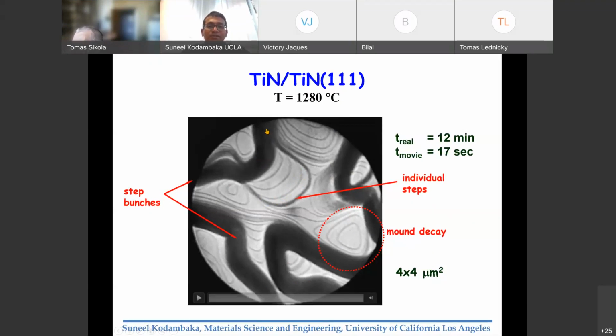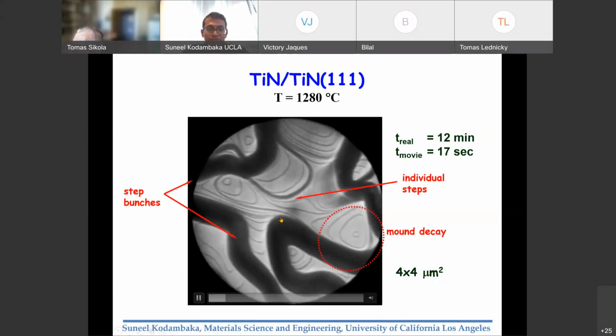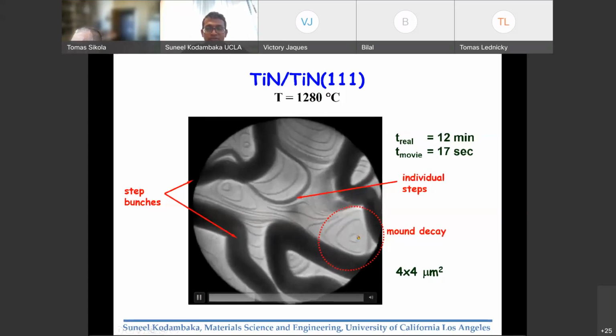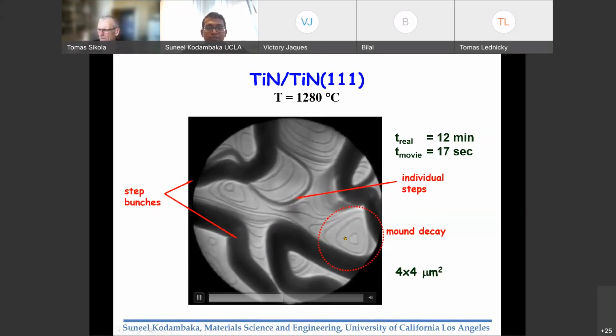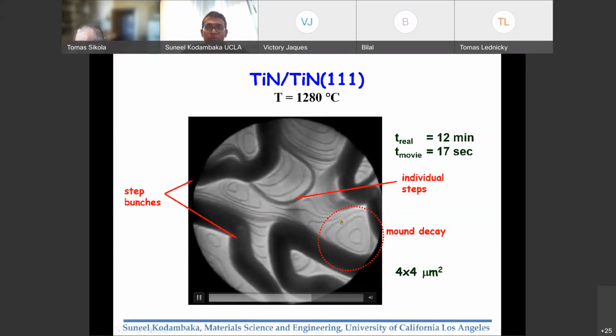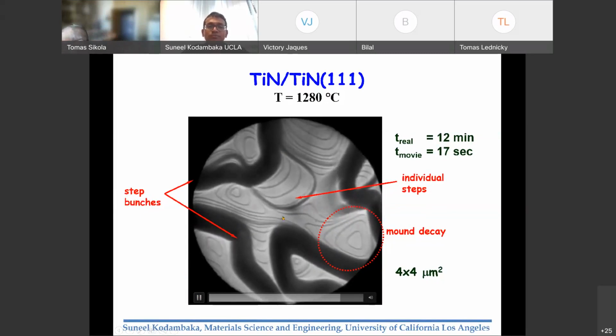These darker lines are thick step bunches and grains within this film that was deposited on the sapphire crystal. And what you're looking at here is the decay of these, what I call mounds. In LEEM, you're looking at a two-dimensional projection of a three-dimensional surface. So these are mounds, something like a wedding cake where you have a stack of islands on top of a terrace. When we are annealing this, we observe a lot of step motion and the disappearance of these islands and a continuous flow and rearrangement of the surface. As time progresses, the surface eventually gets smoother.